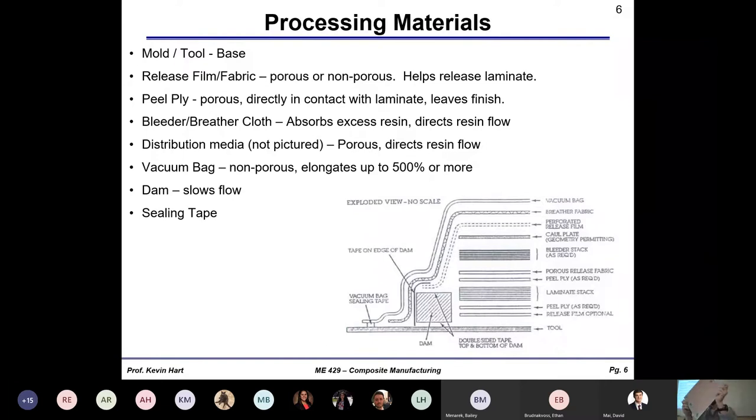Okay. So we see the aluminum. We see the thin pink looking release film. And so this is how this thing was built up. You have this aluminum plate, this pink release film. And then I placed all of this wet, this was originally wet fabric, onto this release film, just like this, all right? On top of that, we have to have another release layer, but that release layer needs to be porous because if there's extra liquid resin in there, we want to squeeze that out. And so we place that porous film over the top of that, and then we place our bleeder cloth on top of that to absorb the extra resin. And I peeled both of these together off of the composite after the manufacture, and that's what you see here.